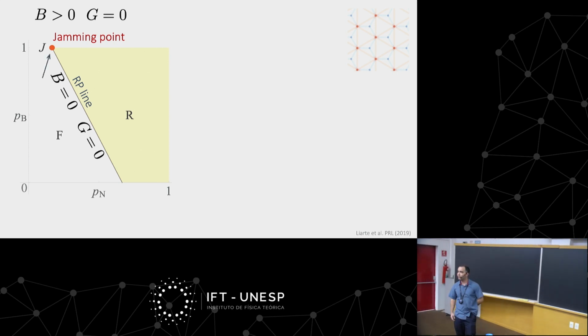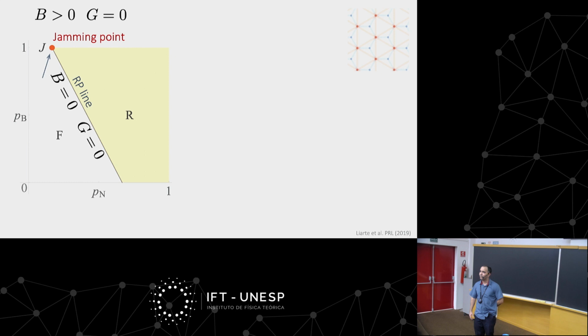Sorry, there's some randomness in this, right? Because PB doesn't tell you which bonds I break, right? PB is the probability of assigning a bond for the honeycomb lattice. Right, but yes, it's randomly chosen. So isn't there some error? I mean, there's an error bar, right? Depending on how you choose PB, depending on which bonds you break, doesn't it give you a different answer? In a real system, if you do a simulation, for instance, there is an error bar, and really, there are other subtleties. For instance, there are some regions that are over-constrained, regions that are under-constrained. There is all of that. But this is an analytical theory, an effective medium theory, and in this theory, there is no error bar.